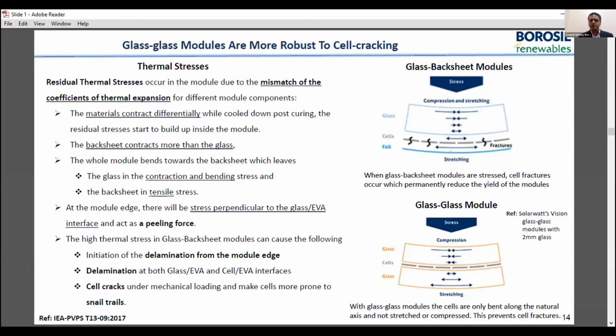These stresses are perpendicular to the glass EVA bonding. So of course, the perpendicular stresses cause a peeling force to get generated, basically. The high thermal stress in glass backsheet modules can cause the following issues: initiation of delamination from module edges, or delamination at both the glass EVA or cell EVA interfaces. So ultimately, delamination as well as cell cracks might also take place.